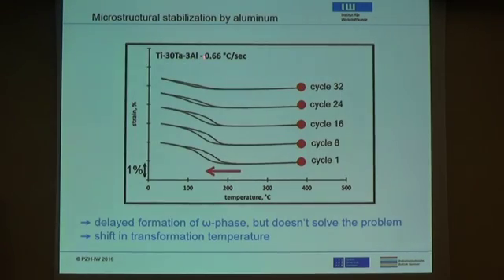So this is a modified alloy, titanium 30 tantalum with 3% aluminum. Again, a fairly slow test. Remember, this was the test where the material lost its properties after 3 cycles. Now with the aluminum, you see the first cycle. The cycle number 8 looks pretty much the same. And it takes around 30 cycles before the material starts to degrade. So aluminum does help. It delays the formation of the omega phase, but obviously it doesn't really solve the problem.